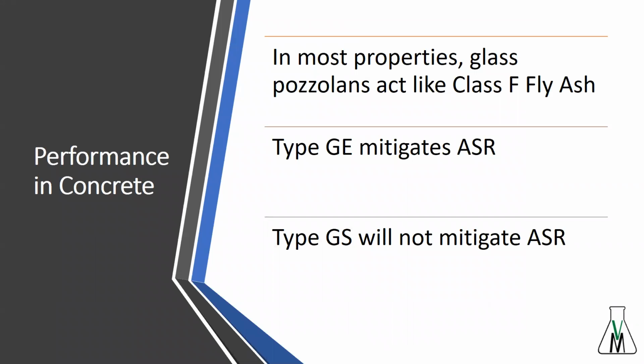So in most properties, glass pozzolans act exactly like Class F fly ash. You can load them at 20 to 30% cement replacement. It is a 1-for-1 replacement of cement. So the embodied carbon of glass is a bit more than fly ash because we have to do somewhat more beneficiation, namely grinding it to convert it into the proper particle size. So let's look at the next slide.